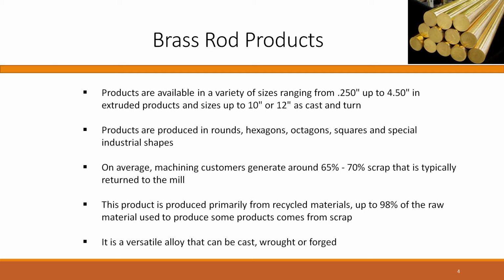For every pound of brass rod that's sold, the industry information is that about 65 to 70% of that is turned away as machining turnings and rod ends, and they all generally get returned to the producing mill because that's good quality input material for our melting operation. And it's an alloy that uses a high level of recycled material.